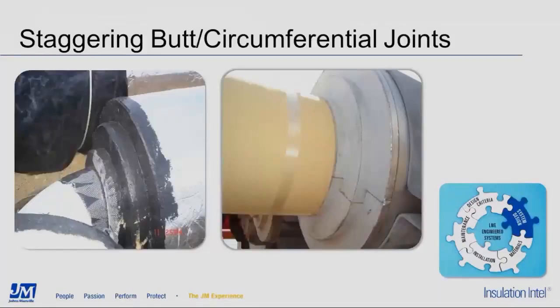Here are some pictures of joint staggering. The left picture shows the butt joint staggering at an elbow location. The right-hand picture is a little harder to see, but it shows the inner layer longitudinal joints at the 6 and 12 o'clock positions, with the neighboring insulation pieces having its outer layer longitudinal joints staggered by not quite 90 degrees, but more than sufficiently.